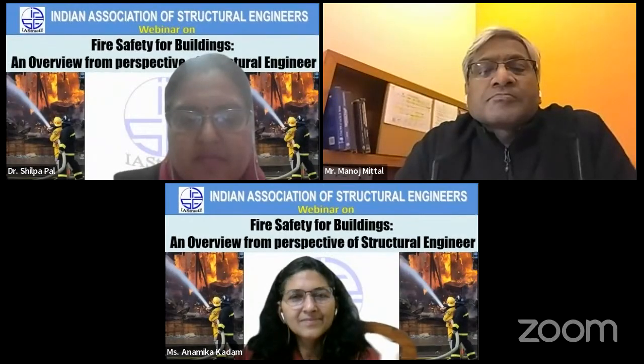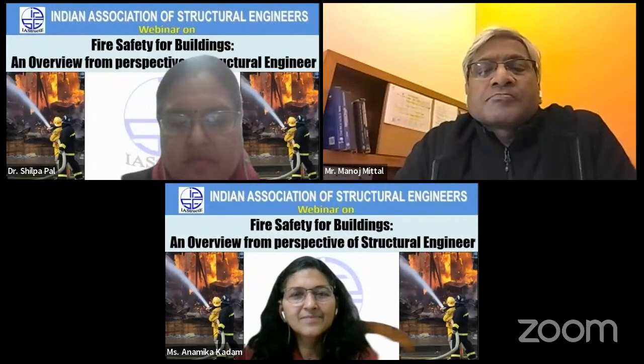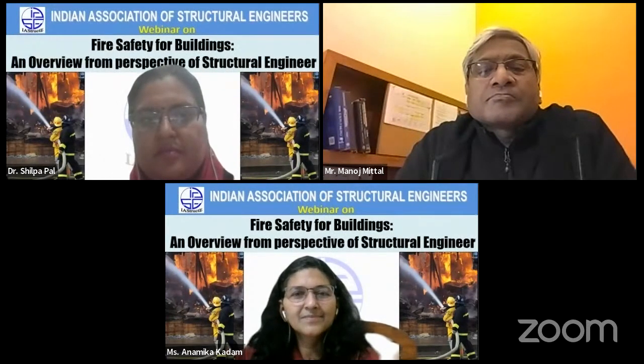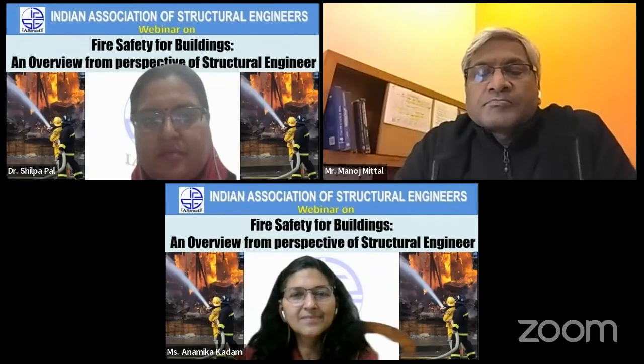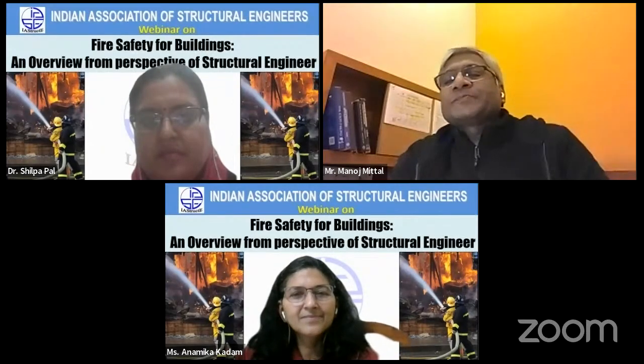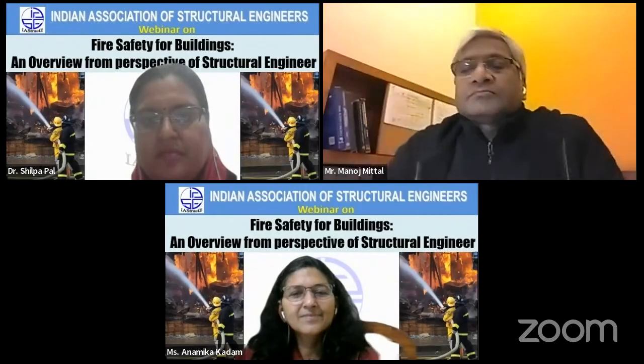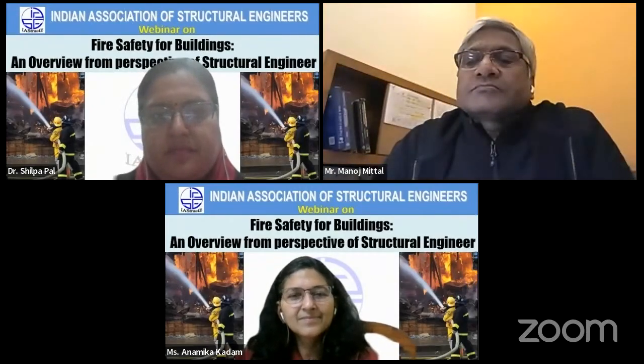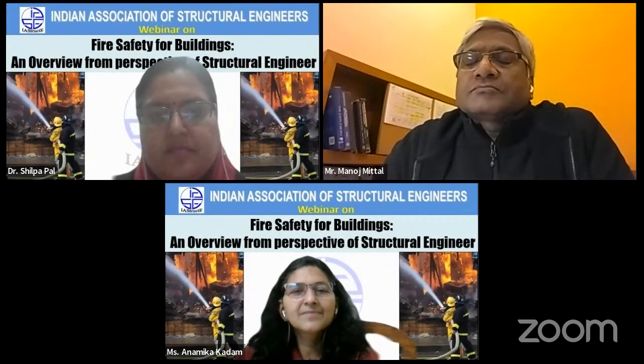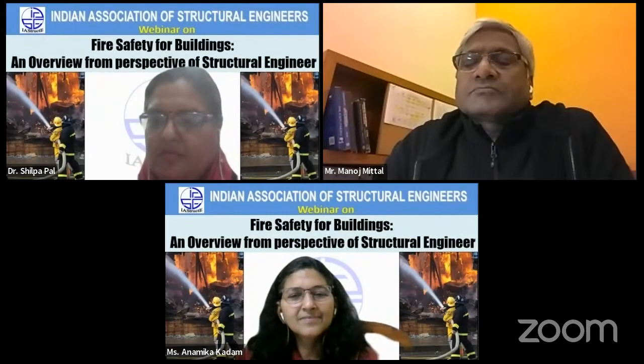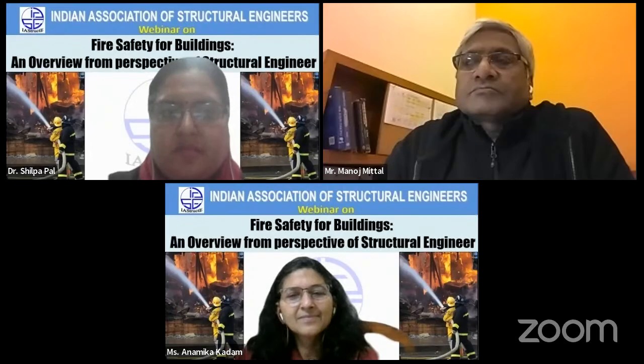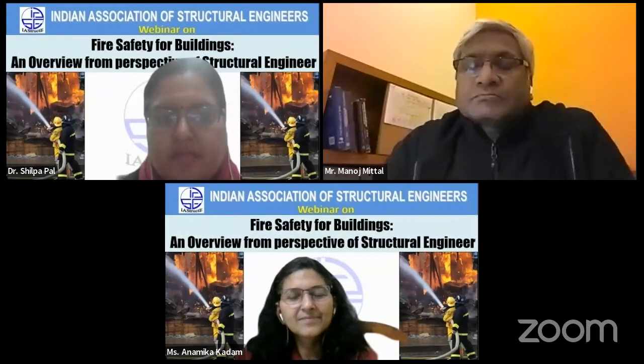by structural failure, that is deformation as well as collapse, nor should it fail by insulation. That means temperature on the other side should not increase more than 140 on an average, nor 180 at any point. And integrity: no crack should come. If it comes, there's a method of testing it. Put a cotton pad for 10 seconds or something like that, and it should not catch fire. CBRI has got a facility to do that actually. I think in Pune there is another lab which has it.